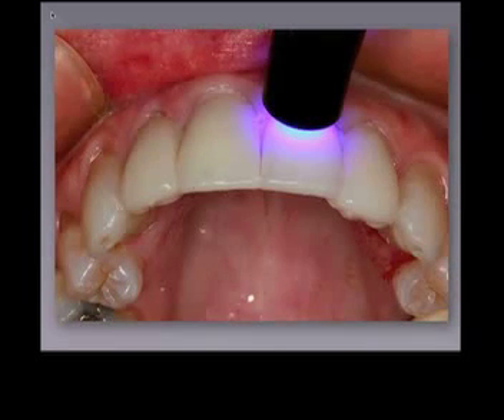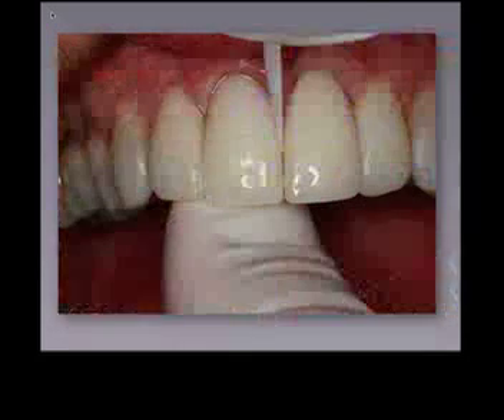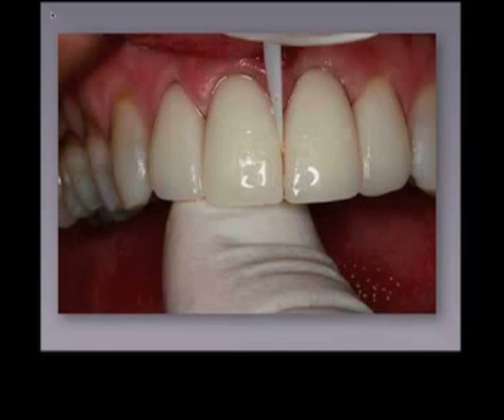So in the spirit of the best bond, final cleanup with flossing should be followed by complete self-cure reaction time. Duo-Link is 5 minutes at 37 degrees. Most dual cure cements vary from this, including RelyX at 10 minutes, Nexus 3. Clinical protocols would need to be adjusted accordingly for many cements, but in this case, you have a nice cleanup and excellent results.